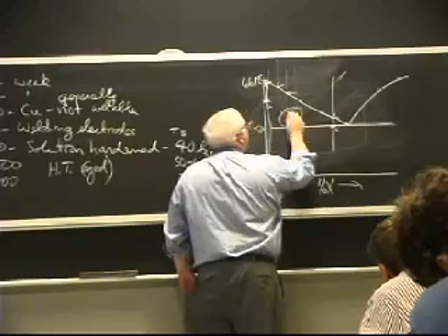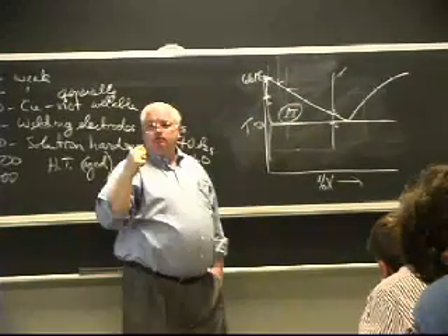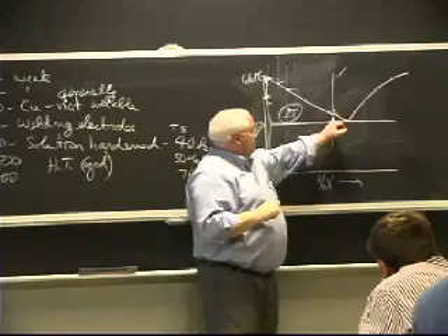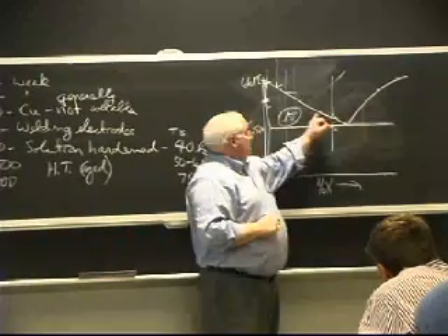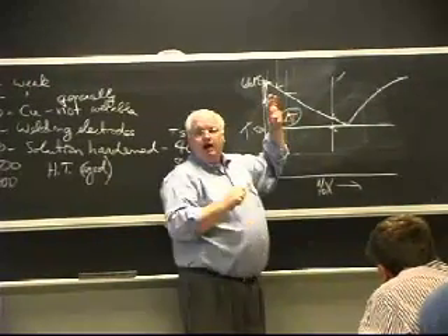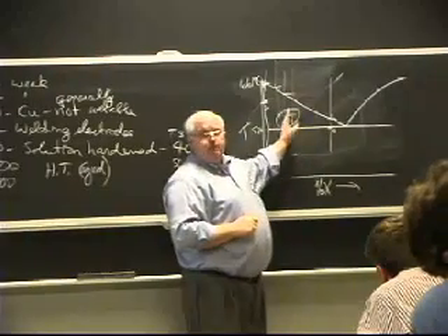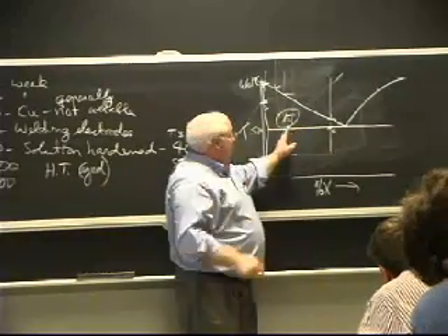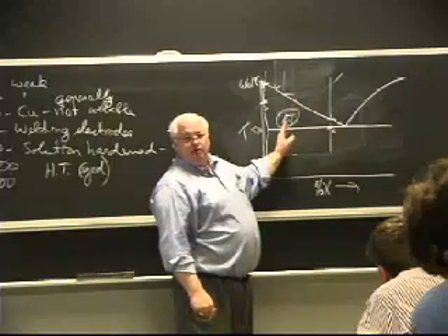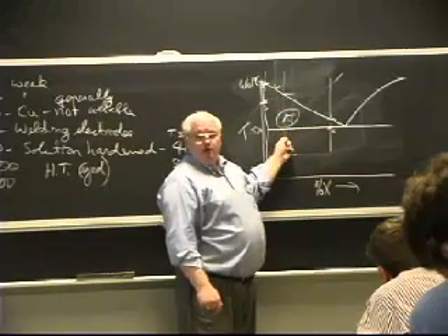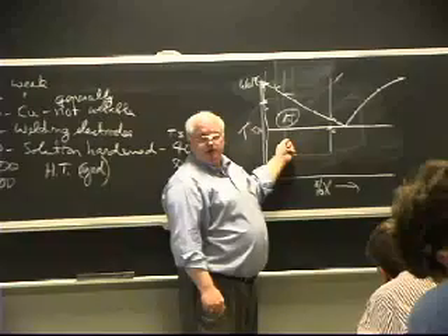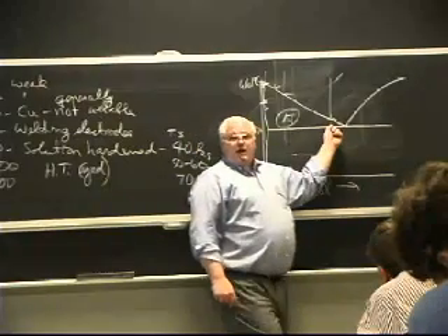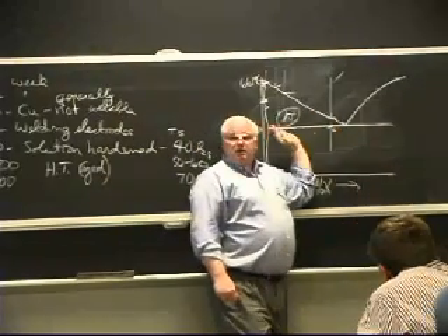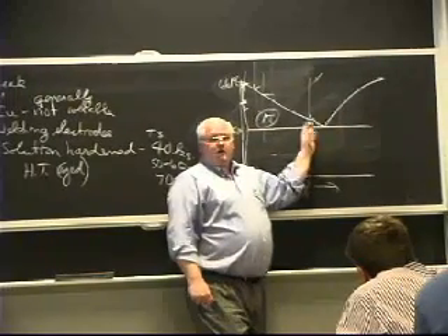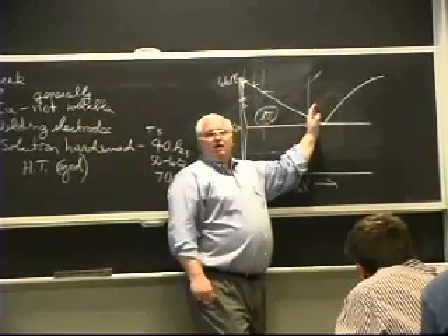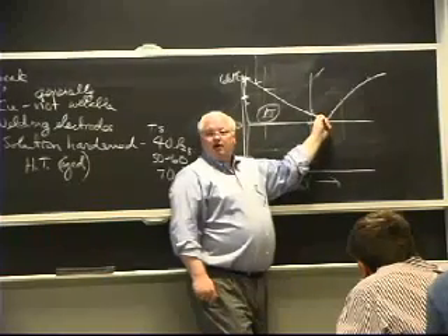If I have a small delta T, not a problem to weld it. So over here, very highly alloyed or very leanly alloyed, I can weld it. If I end up with a weld metal in the middle here, I'm out of luck. A lot of the aluminum copper alloys are designed to be in here for optimum strength. That's why they're not weldable. They don't fail in the weld metal, they fail in the base material. I have a lot of welding electrodes, the 4000 series, where I just dump in 10% silicon into the welding electrode, and that means that weld metal is going to be highly alloyed no matter what. I always have a small delta T.